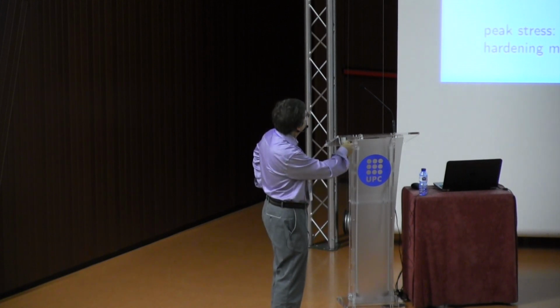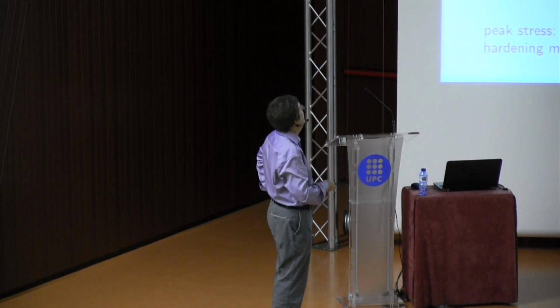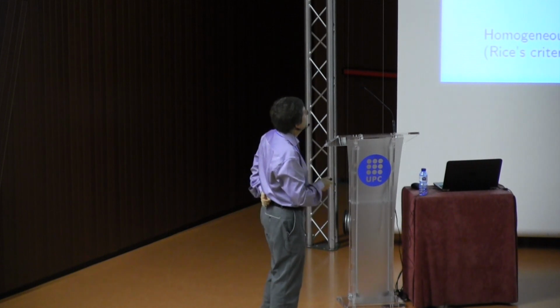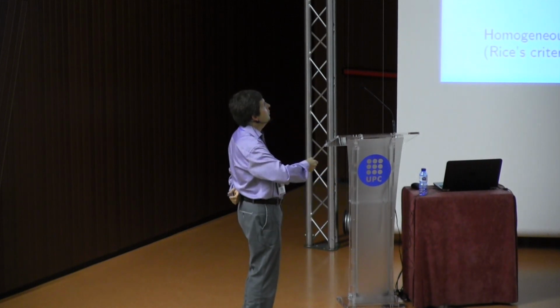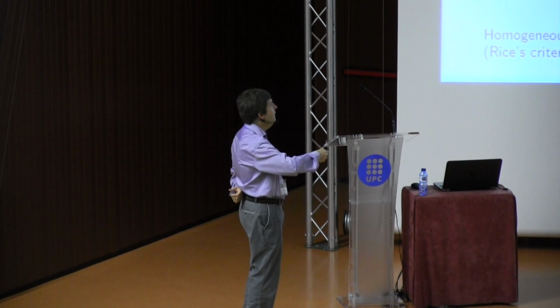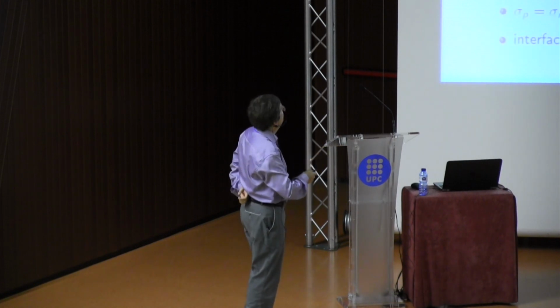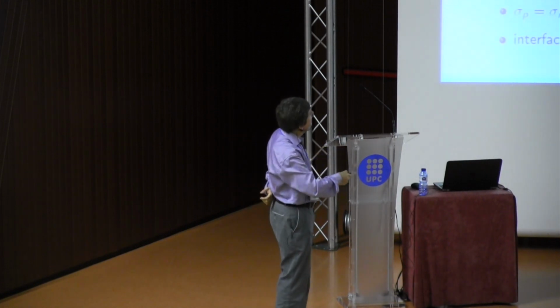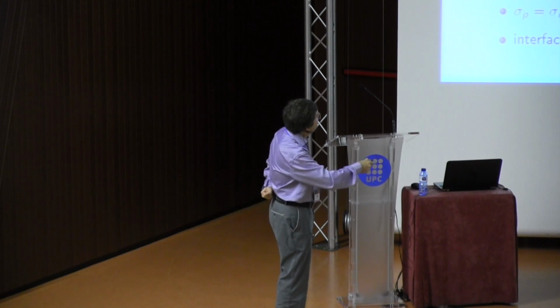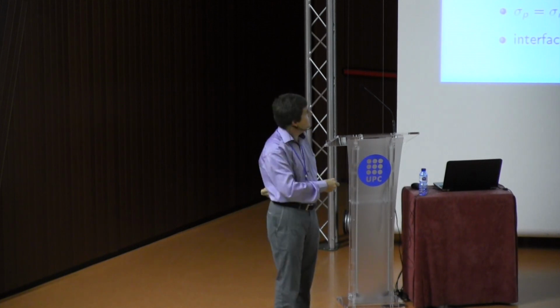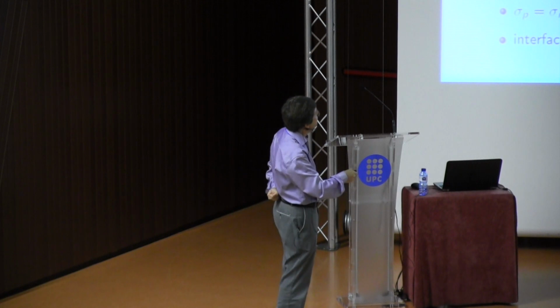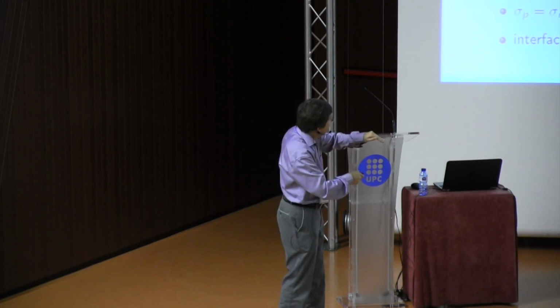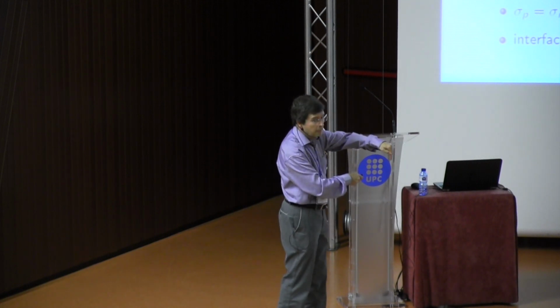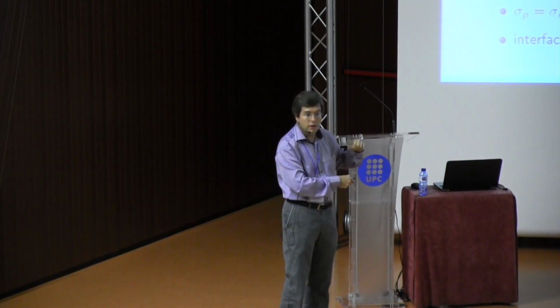But then you take simply a softening hardening law here. And then I will skip the details of the computation, but we take the bifurcation band here, and we compute the profile of plasticity in the zone of the front of the band here. And you see that there are two zones. There is a zone in the front of the band where the material is softening, and behind it is hardening.